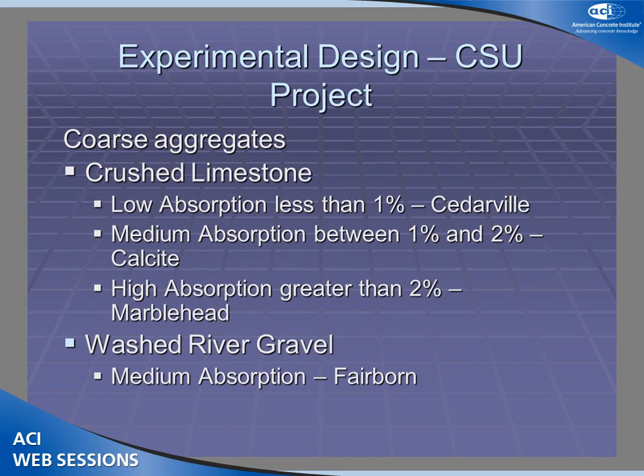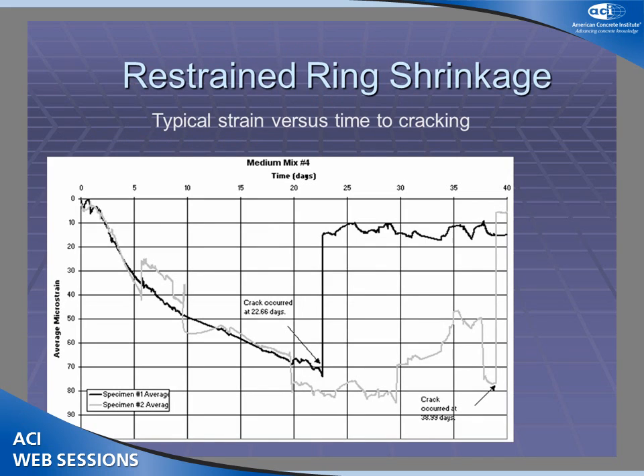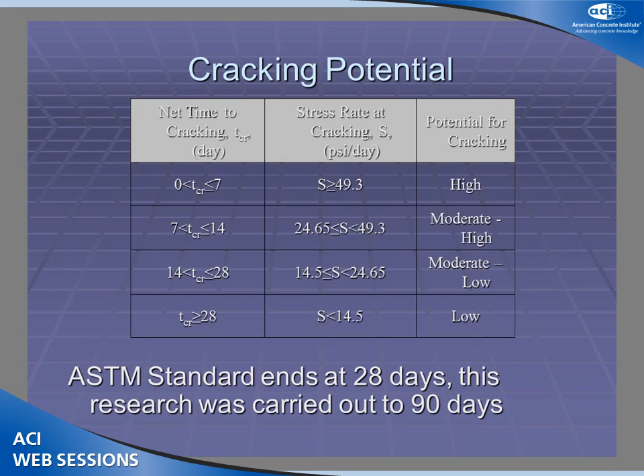And so we got some supplies of aggregates that were commonly used by ODOT, different sources, a low absorption, which is less than 1%, what we defined as medium absorption between 1 and 2, and then we had a material that was relatively high absorption. In Northeast Ohio, they primarily used crushed limestone. The state wanted to look at this in a broader sense, and in other parts of the state, they use river gravel. We could only find one with a medium absorption. And we did a number of ring tests, and sometimes looking at the time of cracking and so forth, and sometimes in the duplicate rings the cracks occurred together, and sometimes not so much. We crunched all the numbers and looked in terms of cracking potential.